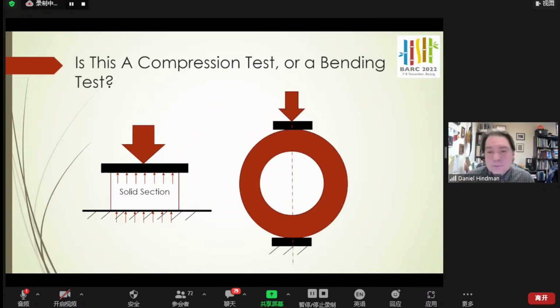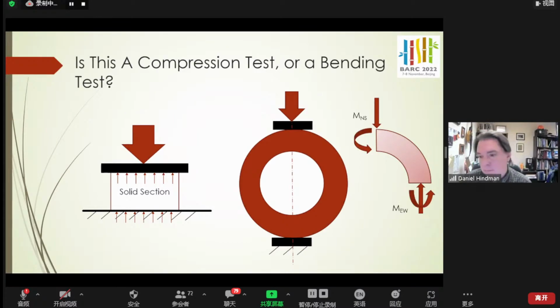However, as we think about a ring being compressed, if we take a quarter of that section and look at the forces on that quarter, we'll have a force from the top of the ring vertically, but then the corresponding force is going to be at the center of the ring with a moment arm, the distance of the radius. So what happens as you compress these rings is that that moment becomes the critical force within the ring, and that's what causes failure. So you tend to see a splitting of the rings, either what's called the north-south, which is the top and bottom, or the east-west, which is the right and left.